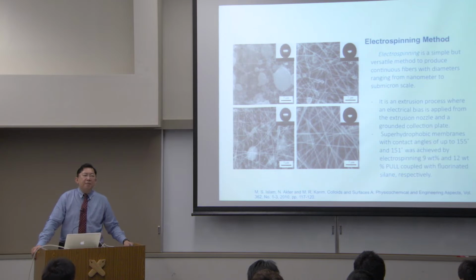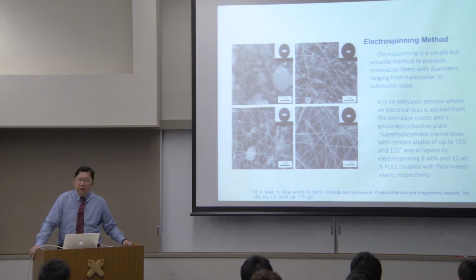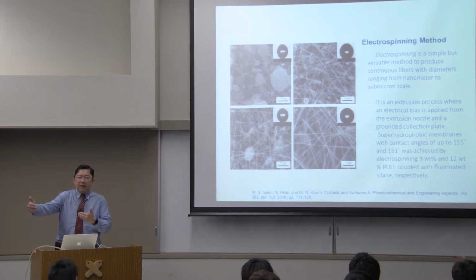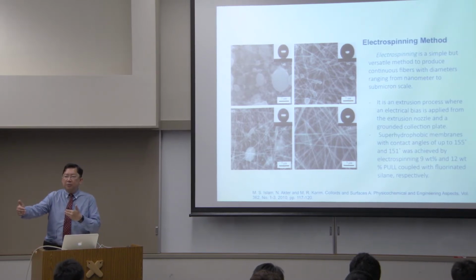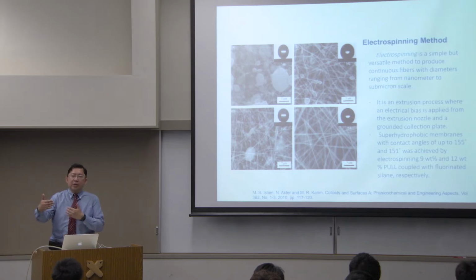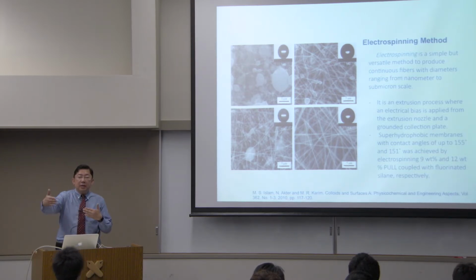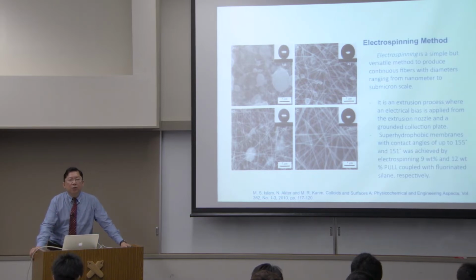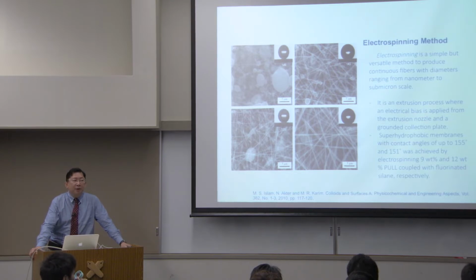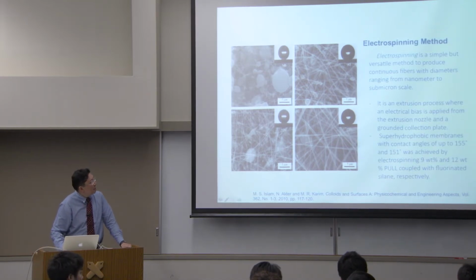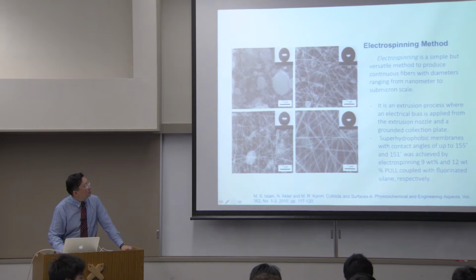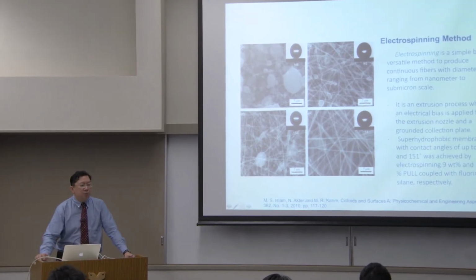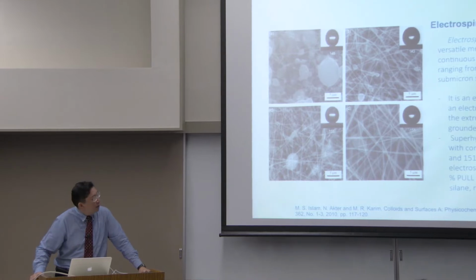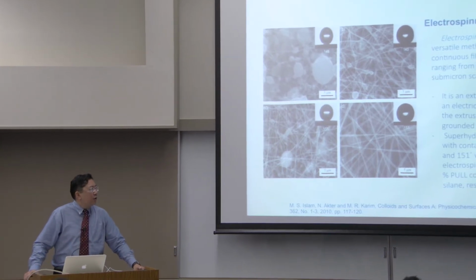So electrospinning makes use of a high voltage between the target and the solution source, let's say 10 to 20 kilovolts, such that during the injection or exit of the solubilized polymer, you form very thin or ultra thin, if not nano, fibers. These nanofibers provide different types of volumes and roughness that allow one to have also a high contact angle.